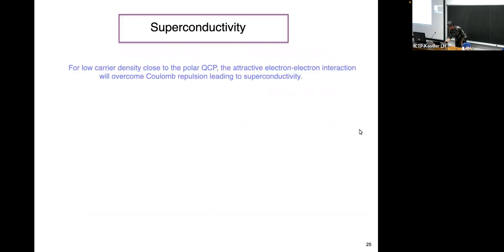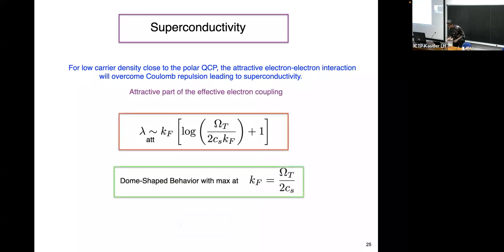Okay. So superconductivity. For low carrier density, we'll see that the attractive interaction can overcome Coulomb repulsion, but let's just look at the attractive part of the effective coupling. The attractive part of the effective coupling goes basically as KF log 1 over KF. That's a dome, which is very familiar for those of us who played with BCS equations. We'll have a maximum when KF is of order the cutoff divided by 2CS. It's that log that's crucial. That's why I kept hammering about the log. The log has an argument that's density dependent, and KF goes as n to the 1/3.